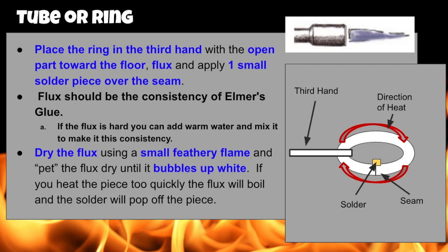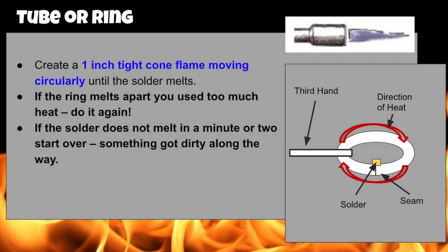Next, you'll take a tweezers and put the ring in the third hand. Then take the flux brush, flux the tube or ring, and place one piece of solder across the seam. It should be on the inside of the bottom of the oval. Dry the piece with a feathery flame. Then use a 1-inch cone flame moving in concentric circles perpendicular to the piece. The solder should melt very quickly.